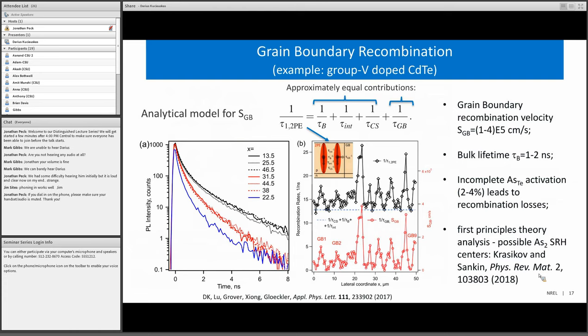The overall impact of the bulk recombination, interface recombination, and charge separation in this case is about equal to the grain boundary recombination impact. Now, this probably happens because in this data, which is now a couple of years old, the arsenic activation was not very high. It was about 2 to 4%. There was a lot of unactivated arsenic. It is likely accumulated at the grain boundaries, and because of that, arsenic-related defects at the grain boundaries were a recombination site. First principles analysis done by Dmitry Krasikov at First Solar suggests that arsenic dimers could be these Shockley-Read-Hall recombination centers at the grain boundaries.